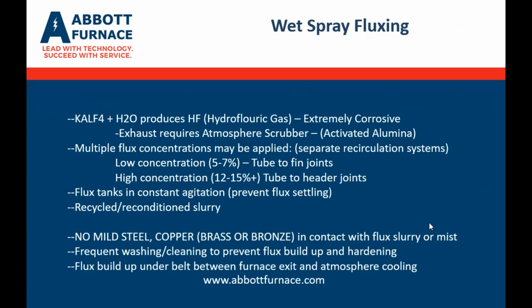The flux tanks are used to keep the flux in agitation and to keep it at the proper ratio. One of the issues with flux is it gets very hard if it settles, and it's very difficult to clean. You're basically going to have to take a chisel and hammer to clean off the flux where it begins to build and is allowed to harden. So part of the job of the fluxer is to keep the flux in constant agitation to prevent any kind of flux settling.